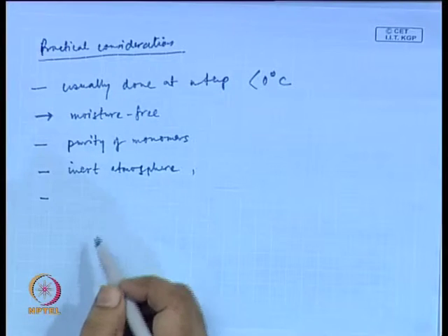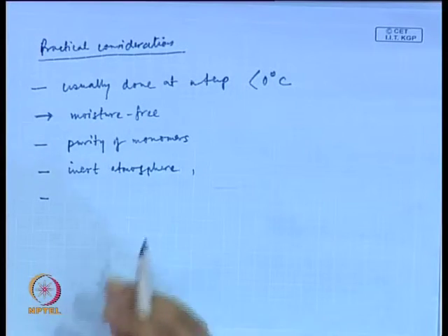For cationic chain reactions, you can make arrangements to perform the reaction. You might have to arrange or purify the monomer and the gas, nitrogen or argon, and you have to make the container or the reactor moisture free. For that you may spend a lot of time, but the reaction happens very quickly, within seconds, and because it happens so quickly, it generates a lot of heat, and sometimes this heat management is also a problem.